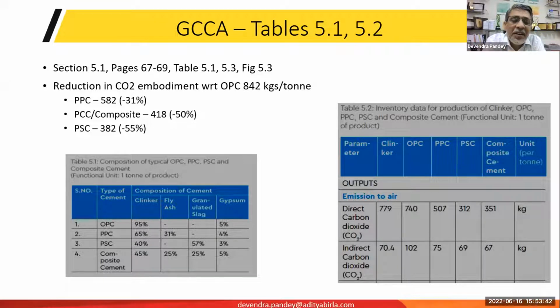The first slide, basically, was covered a little while back by Mr. Venkatagiri also. This is from the latest publication which GCCA has done, and it basically captures the composition of OPC, which is ordinary Portland cement. PPC is Portland Pozzolana cement, which has about 31% fly ash in it. Portland slag cement has about 57% GGBS in it. Composite cement has around 50% of fly ash and GGBS combined in it.